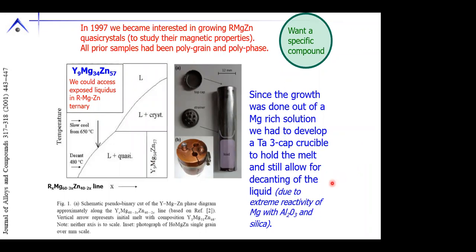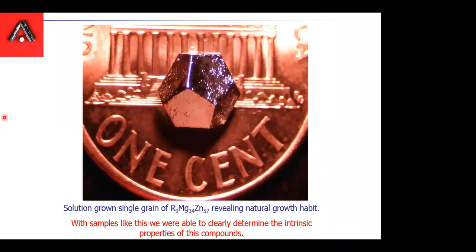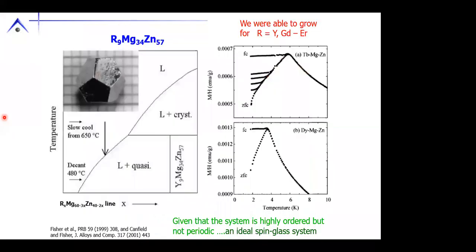Okay. Now, with that done, we were able to grow beautiful single grain quasicrystals. These were some of the first large, naturally faceted icosahedral quasicrystals. And in addition to being incredibly aesthetic, and this became one of the archetypical images of these, we were also able to do the basic physics on them. So we could grow these for non-magnetic yttrium, non-CEF split, in other words, Heisenberg-like gadolinium, and terbium through erbium. And what we were able to find was, with these highly ordered, albeit aperiodic sublattices of rare earths, we could have classic model spin glass physics.